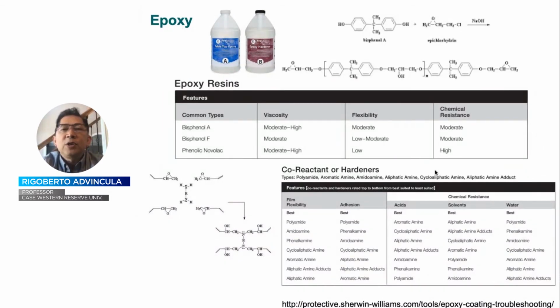Once you have the epoxy group, this can then be cross-linked with, let's say, diamine, or what we call a co-reactant or hardener, and then that gives you a very good thermoset coating, or a coating that's based on a cross-linking mechanism. And there are many types of epoxy variants, different types of hardening material. The bottom line is epoxy not only belongs to a large family of coatings, it is very popular also, of course, in the carbon composite or fiber composite industries.